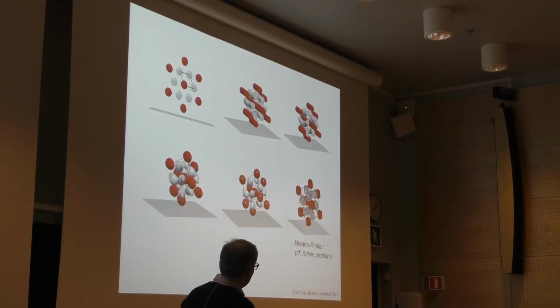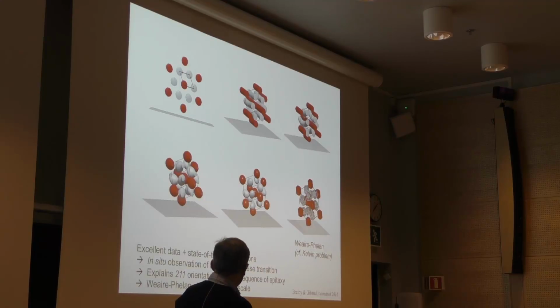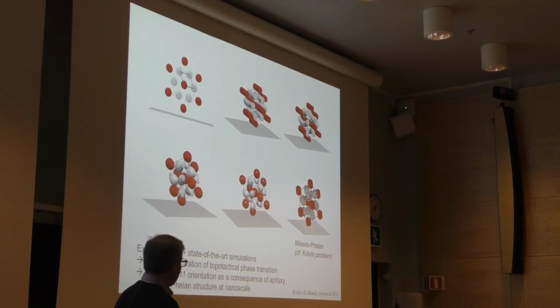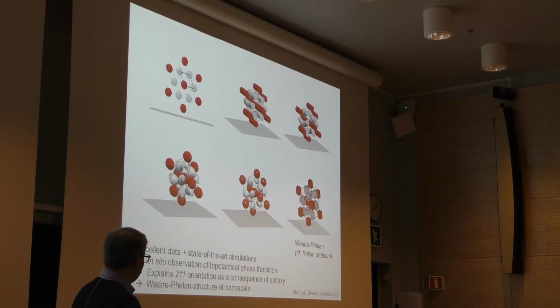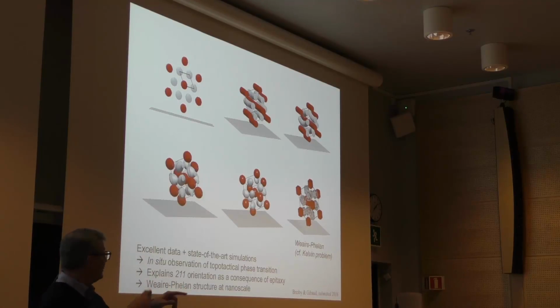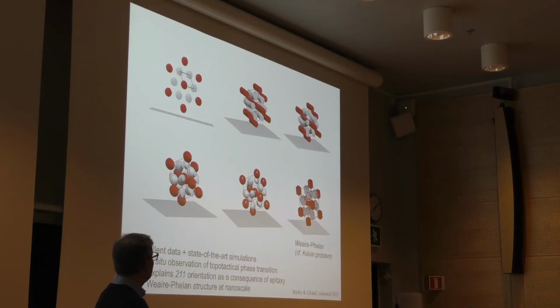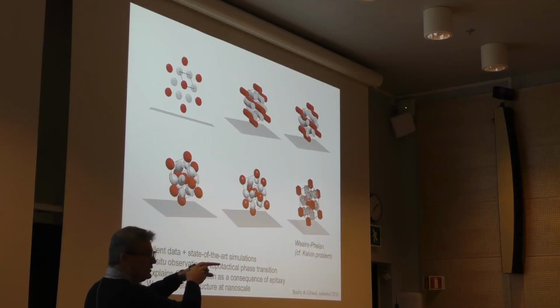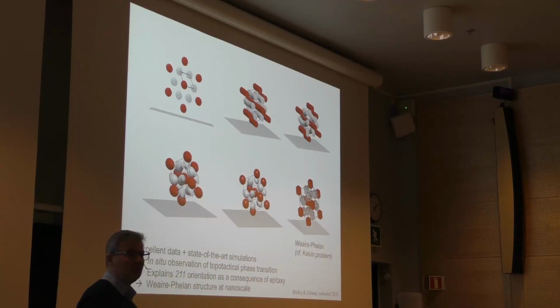And what is also worth noting here is that this has a very particular orientation with respect to the substrate. It's a 2-1-1 orientation, but this is then fully consistent with the simulations that I just showed you, that the contraction is really taking place along these original cylindrical micelles.